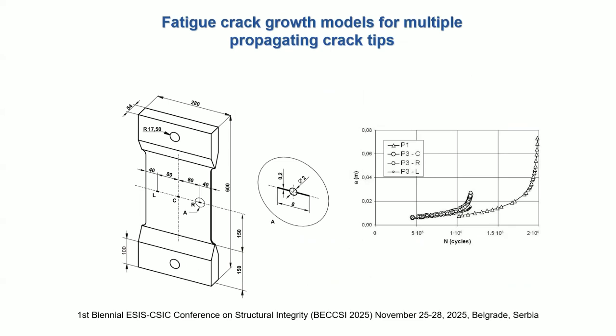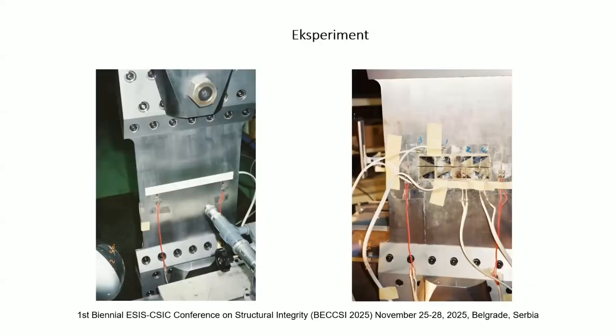And for specimen with 3 cracks, this is the experimental result, and we want to simulate fatigue life now. But basically with 3 cracks, it comes to what I mentioned at the beginning, and what also Dr. Son mentioned, interaction of the cracks. How can we model interaction? You can use the extended finite element method. And sometimes you don't have everything under control, but you have an analytical model which is perfectly under our control, and we will learn how it works. So this is basically the crack before the experiment and after the experiment.